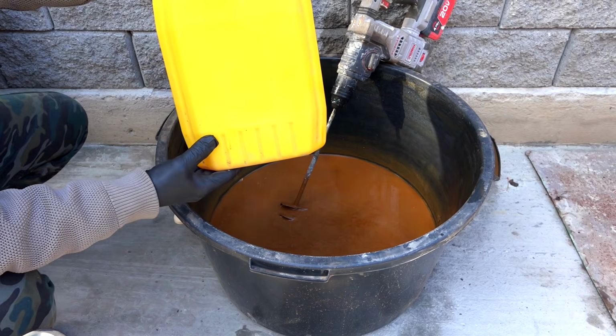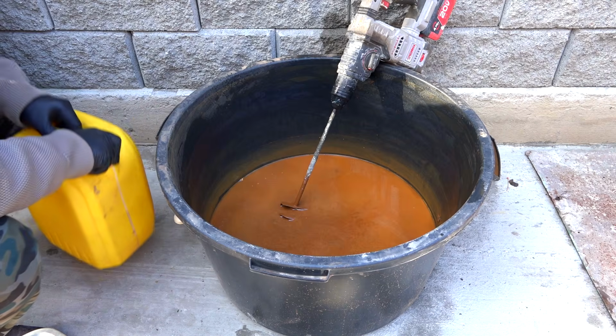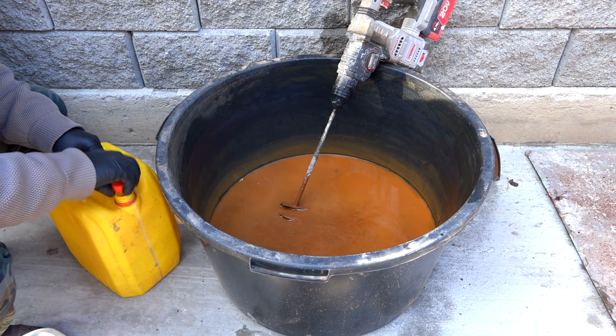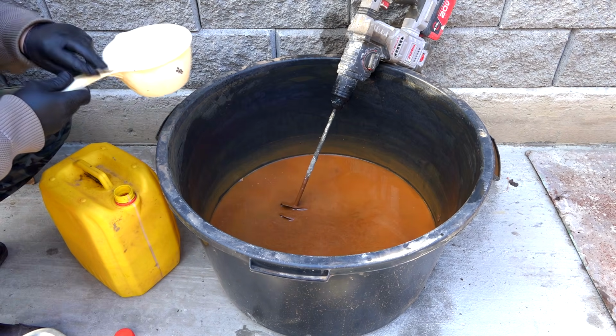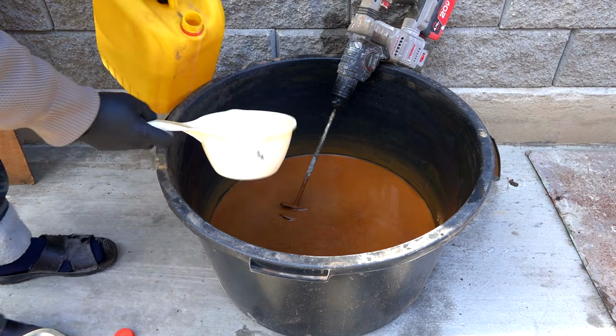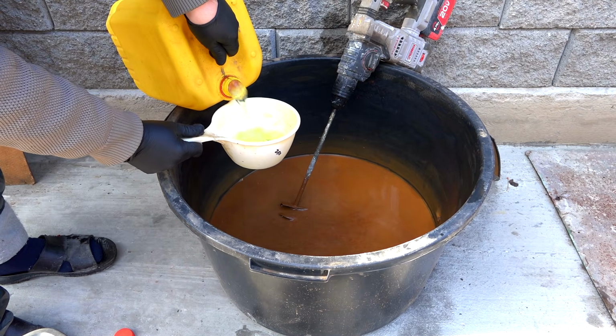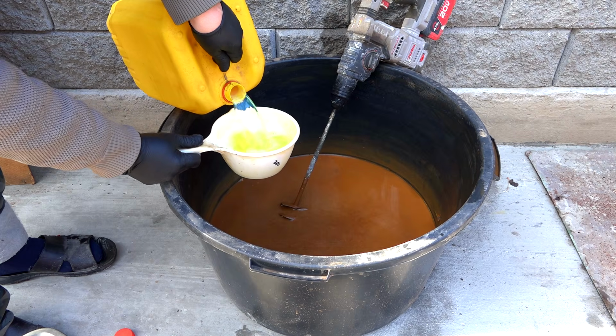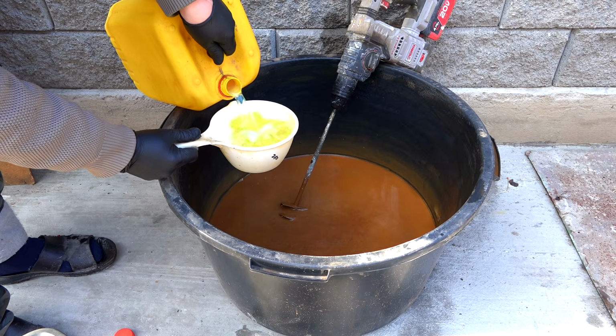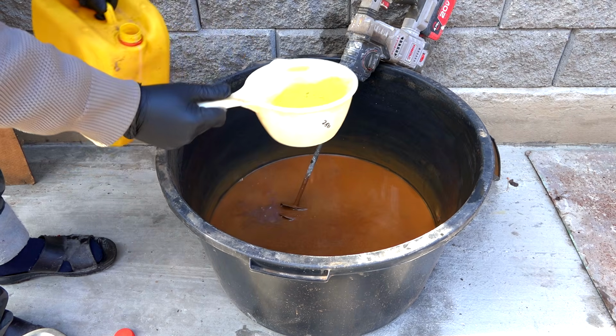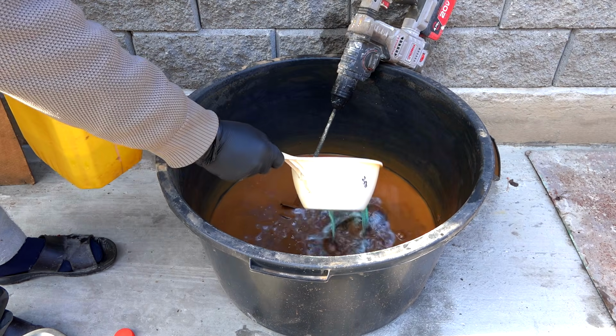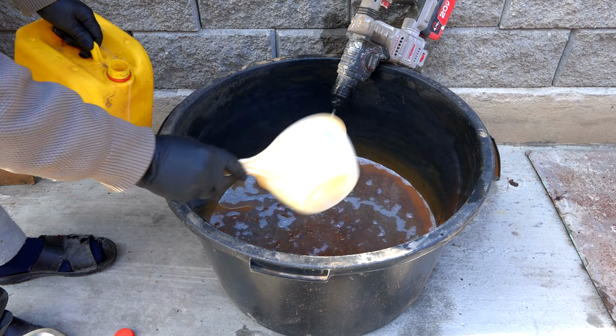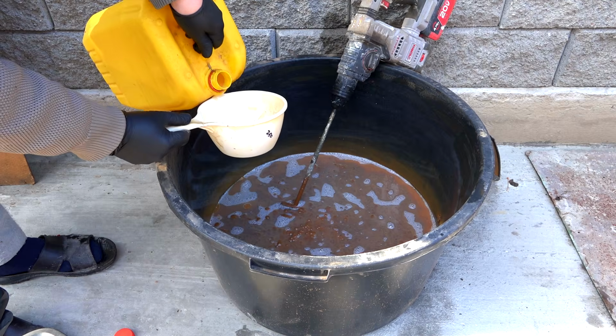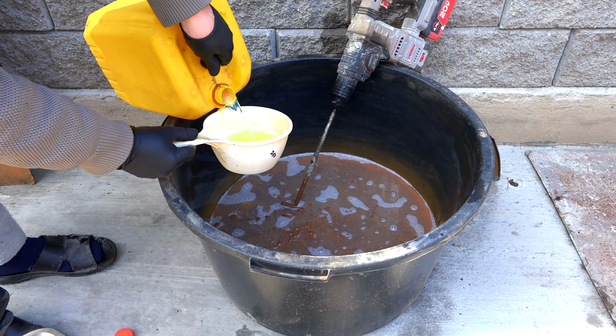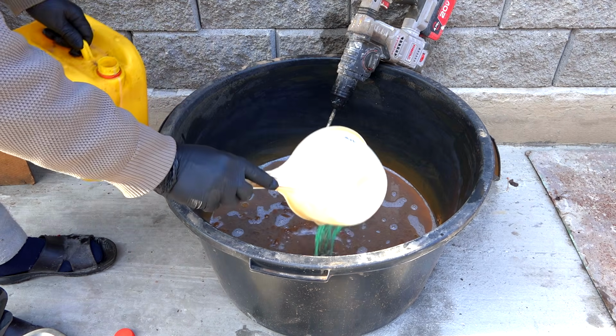This yellow canister contains the liquid I'll be using to extract precious metals. I'll be using oil flotation, and the diesel fuel in this canister is perfect for this. Diesel fuel is quite fluid, wets metal particles well, and thus captures them, floating them to the surface to form a precious foam. For example, using motor oil or any other oil for flotation won't work, as the oil's density is too high to easily and freely wet non-ferrous metal particles the way diesel fuel or gasoline does.